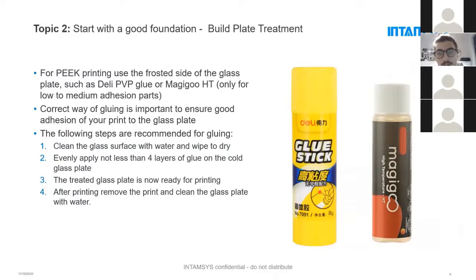Gluing itself is very easy. You should apply 4 layers of glue. First, you clean the glass plate. Clean it only with water and soap. Don't clean it with special glass cleaners that may have a lotus effect. This can be negative to the adhesion between glue and the glass plate. And then apply 4 layers of glue. Between each of these 4 layers, you should wait 30 seconds to 1 minute so that the glue has a chance to dry. After this, your plate is ready for printing. And after printing, when you remove the print, you can clean the plate again and repeat the step of coating with glue.